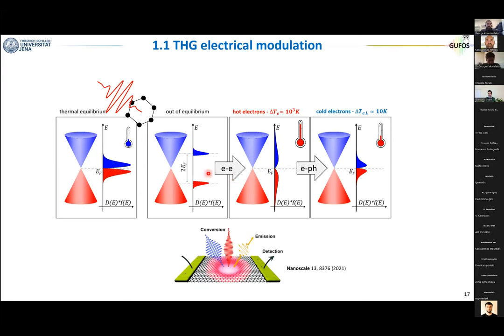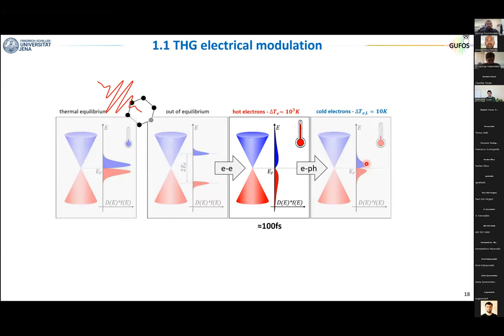Next, you have electron-electron scattering, and this builds up the so-called hot electron distribution. So it's a situation where the electrons are described by Fermi-Dirac statistics, but this time with a very high electronic temperature. And finally, by electron-phonon scattering, you relax, so you transfer the energy to the lattice, and electrons and lattice will have the same temperature. Now, when we do our third harmonic experiments, we use very short pulses in the range of 100 femtoseconds. The third harmonic is generated only within the pulse duration. And this means that in our experiments, the electronic distribution is dominated by this very high temperature.